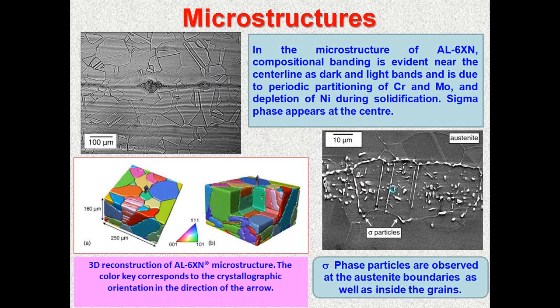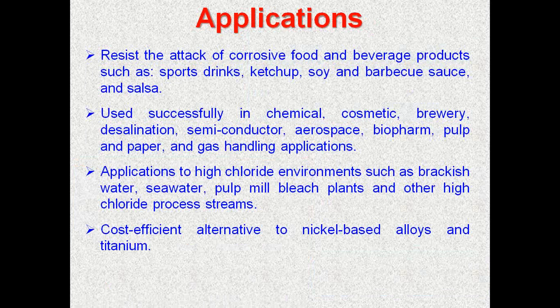But you must remember, as the higher alloying elements are there with chromium, nickel, molybdenum, copper, and nitrogen, the cost is also many times higher than a typical austenitic stainless steel. And it is rightly chosen for brackish water, seawater, pulp mill, bleach plants, and other high chloride process streams. It is definitely a cost-effective, cost-efficient alternative to nickel-based alloys and titanium, because they are much superior in cost compared to Inconel and the Hastelloy alloys and Haynes alloys, many other varieties. The superaustenitic stainless steels are economical replacements.